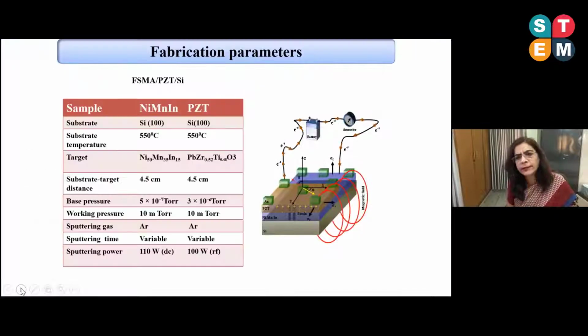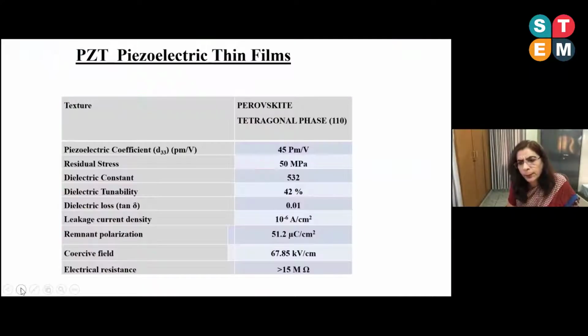These are all the optimized parameters over the 2-inch silicon wafer for FSMA PZT heterostructures. These are important properties for these films, like the piezoelectric coefficient, residual stress, dielectric constant, tunability, loss, leakage current density of 10 to the minus 6 ampere per centimeter square, and coercive field of 67.85. These are the best optimized parameters for these PZT piezoelectric thin films over the 2-inch silicon wafer.